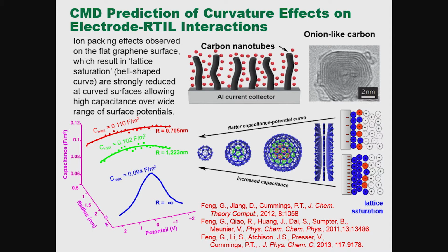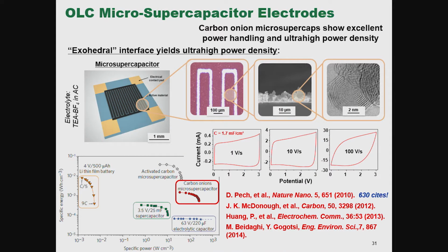So you get this camel-shaped capacitance curve as a function of surface potential. But as you make that surface curved and shrink the radius of curvature, you get higher and flatter capacitance behavior from the same material in a sense. This is surface normalized, and so we can get capacitance over a much wider potential window than we can achieve with a flat surface.